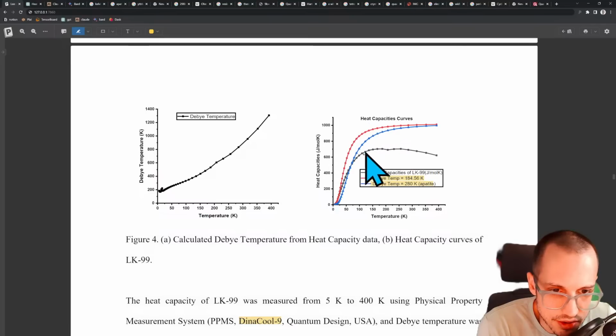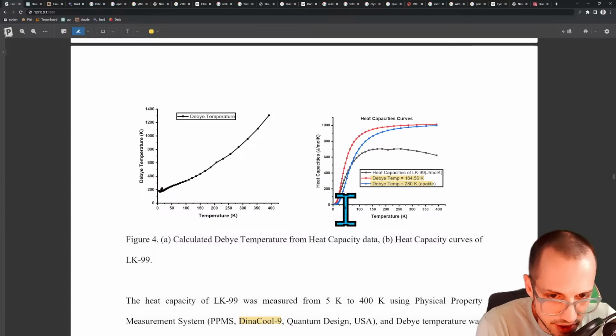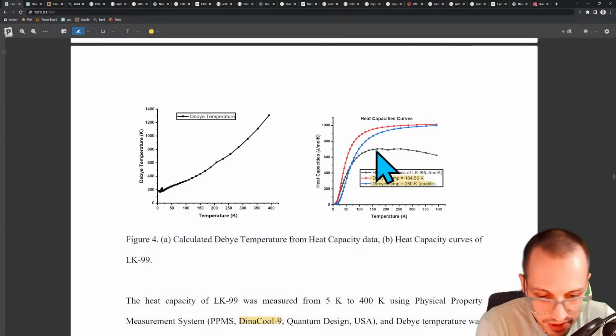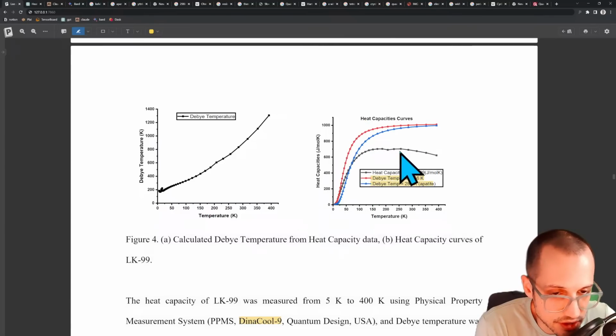So blue is the normal Debye temperature, and then this gray one is the apatite, or the LK99. I guess what they're trying to show you here is that the red and the blue both have this property where the heat capacity stays high, but this gray one here, which is the LK99, the superconductor, doesn't do that. You would think that it would keep going up, but it does not. It actually starts going down at some point.